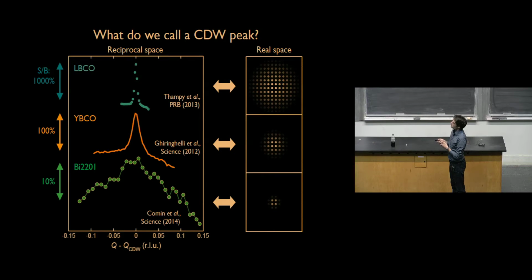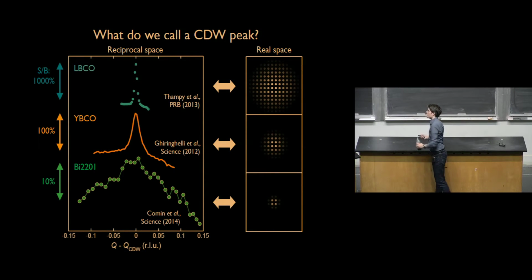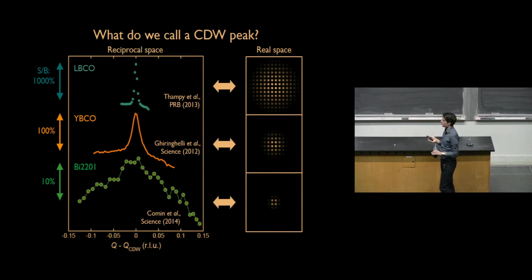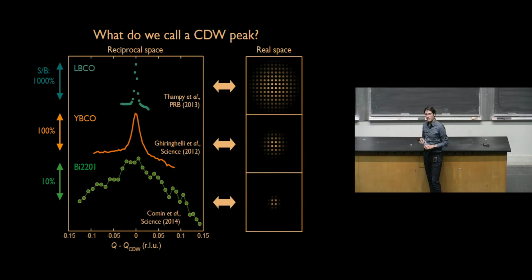But as we went to study YBCO, one of the other cuprate compounds, or Bi-2201, which is one of these bismuth-based compounds, we realized that we're looking at objects which are periodic in real space, but have a correlation length of the order of a few wavelengths. So it's extremely short. This thing oscillates for a few wavelengths, and then its phase slips, and so it doesn't look the same as the original oscillation. So the length scale over which these oscillations of the charge density remain coherent with themselves is only a few wavelengths. It's hardly an electronic crystal, you would say. But it still retains some degree of periodicity in real space, because we see a peak in reciprocal space, even though, as you can see from here, it is very broad compared to, let's say, this very sharp peak.